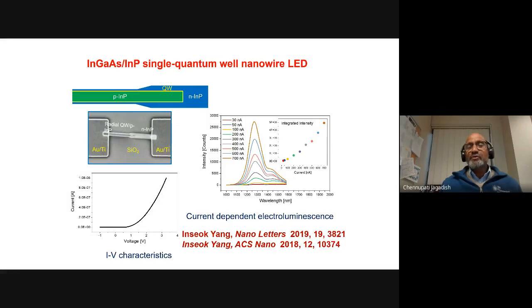The reason for having two peaks is the axial quantum well, which is going on the top of the nanowire, has got a different thickness and composition than the lateral quantum well, which is grown on the side of the nanowire. So that's why I end up having two different emission peaks. It turns out that those emission wavelengths are very good for optical communications applications, for example.